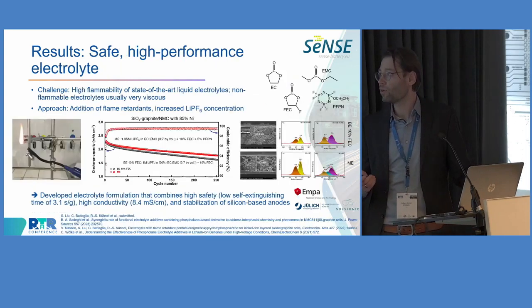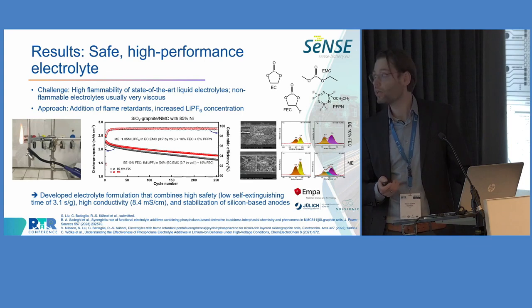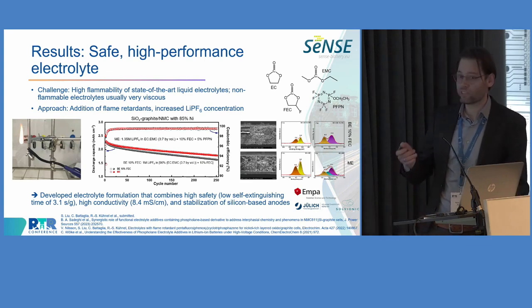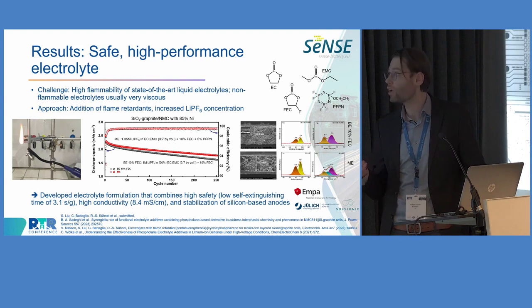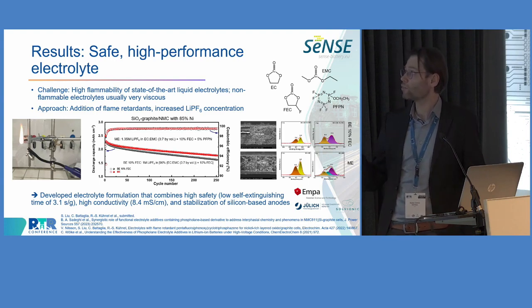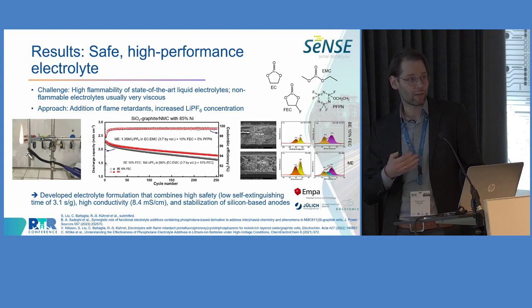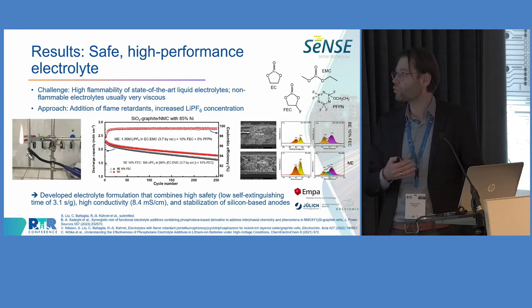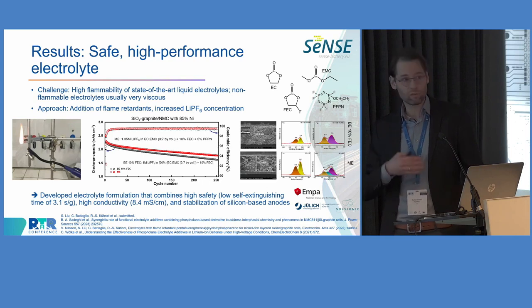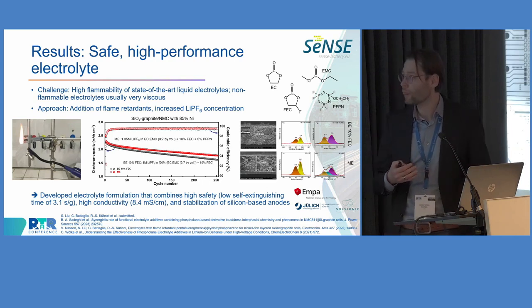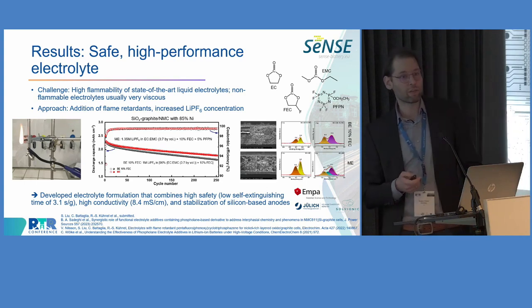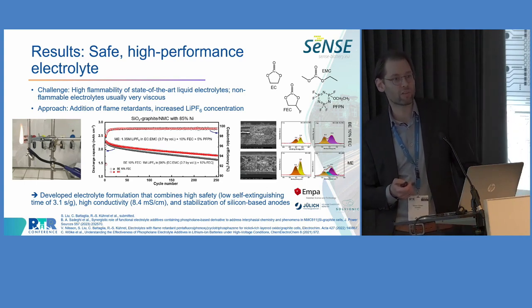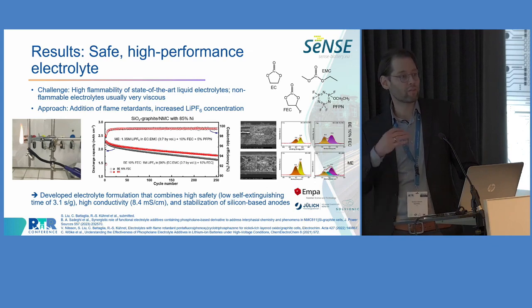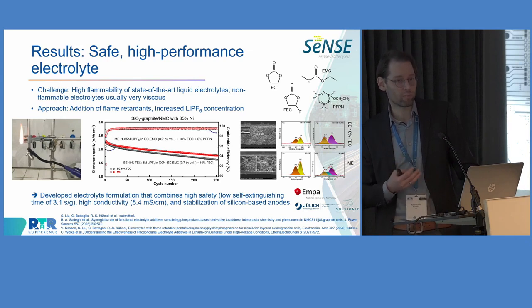The second example I would like to highlight today is about an electrolyte that we developed in the project. So you know, state-of-the-art liquid electrolytes for lithium-ion batteries are based on these carbonate solvents, and especially the linear carbonates are highly flammable. So we were looking for strategies to reduce the flammability of the electrolyte in order to improve the safety of the battery. And there are, of course, multiple approaches, but many of the existing approaches come at the cost of very high viscosity, meaning very low conductivity of the electrolyte, which is then detrimental for the power performance of the cell.